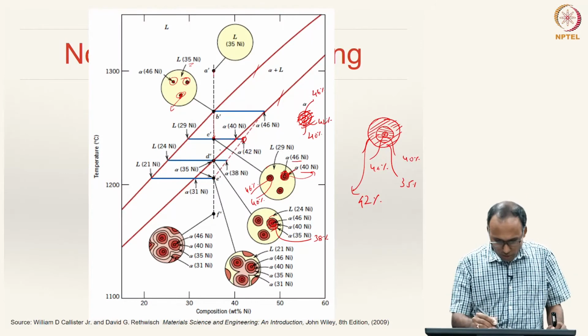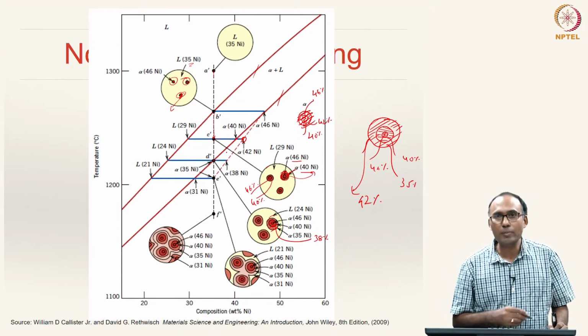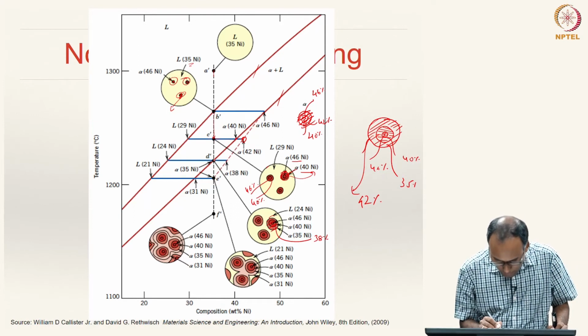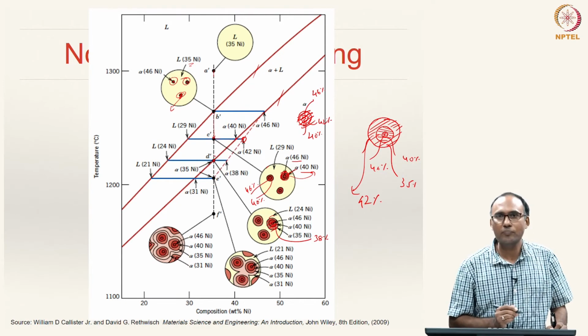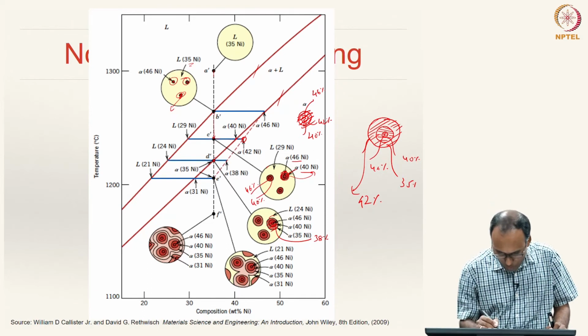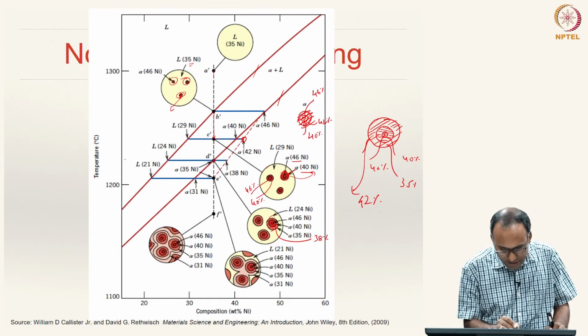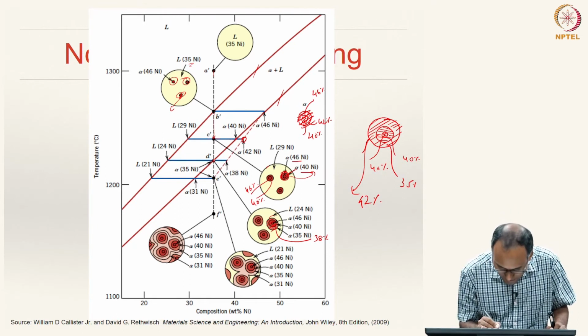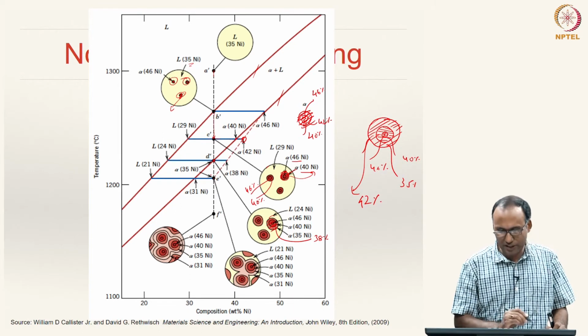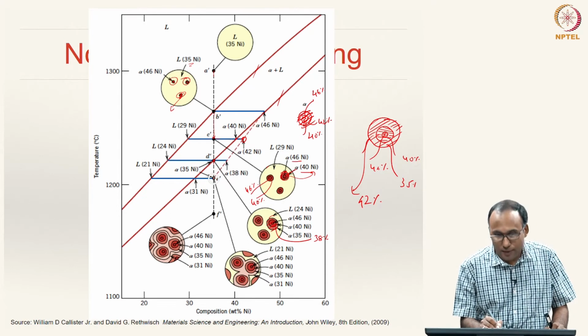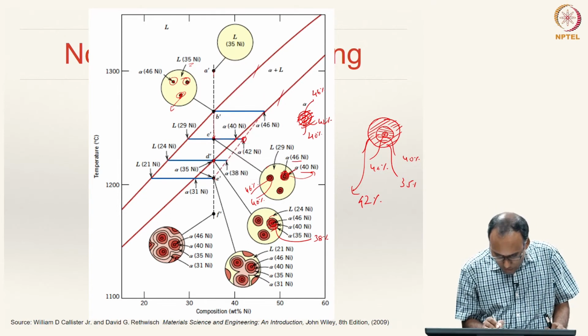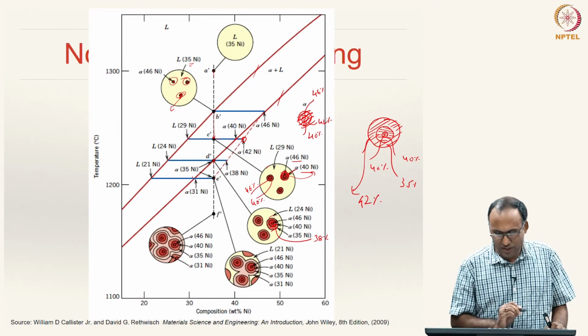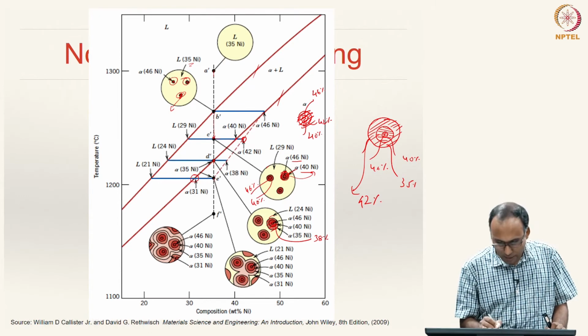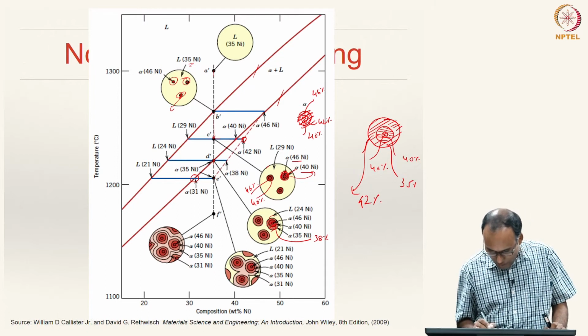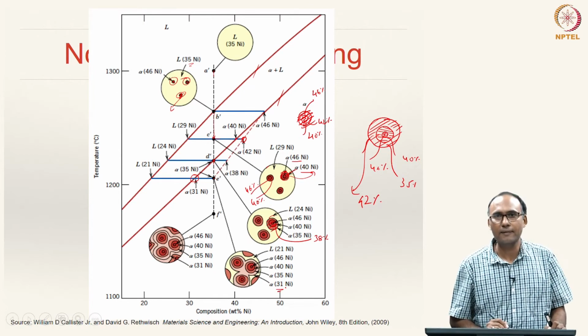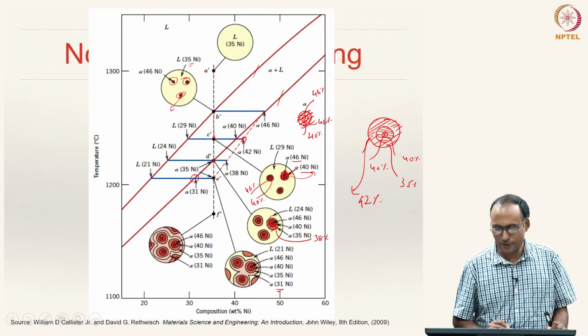All right. So, normally if you are doing equilibrium cooling, you would have finished your solidification at this point D prime, but because we are doing non-equilibrium cooling, the solidification does not end at say 1220 degrees Celsius, but it happens at a much lower temperature, approximately at 1200 degrees Celsius. You need to come down to E prime and there you will have 31% nickel would have been on the solid state, but effectively you will have 35% nickel and hence you will have outermost layer having 31% nickel, right, corresponding to that.